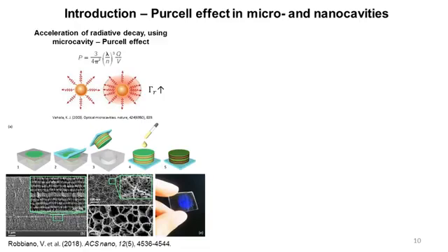In order to increase the photoluminescence quantum yield, it is necessary to increase the rate of radiative relaxation. This can be done by using the Purcell effect. The nature of this effect is an increase in the density of photon states near the fluorophore at the wavelength of its photoluminescence, which leads to a significant increase in the rate of radiative relaxation. One of the most promising methods for its implementation is the fabrication of microcavities based on porous silicon photonic crystals.